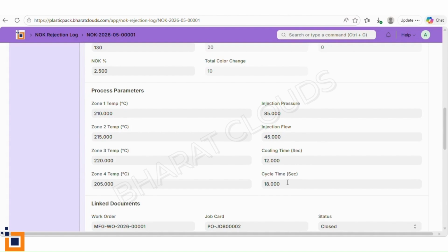When your quality manager sees 45 short fills and then checks Zone 4 was only 205 degrees while Zone 3 was 220. That 15-degree drop near the nozzle could be exactly why the material wasn't flowing fully into the cavity. The data tells the story. And no one had to write this in a register or transfer it from a paper form. The operator entered it at the machine, during the shift, in real time.